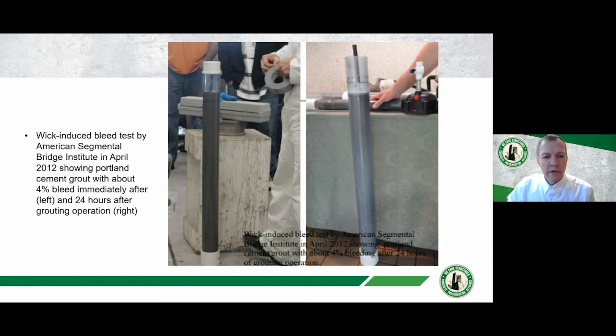One of the common things that lead to voids is what is referred to as bleed. If you have a standard cement water grout, in order to make it pumpable, you actually have more water in the mix than what is required to cure the cement. The result is that after the cement grout is pumped, some of the excess water will essentially float or bleed to the top, and this will end up leaving a void after it either evaporates or is absorbed into the remainder of the grout.